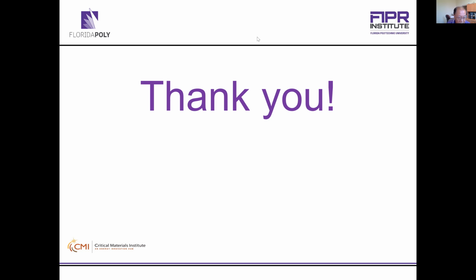Yeah, the first question is from John Carr. The question is, do you have an estimate on the approximate mass of phosphoric acid sludge per ton of phosphate concentrate entering the phosphoric acid plant? Yes, based on industry experience, the amount of sludge generated is roughly 5 to 20%. So that's a large range, 5 to 20% of the P2O5 input. So could be 5% or 20%, depending on how your plant operates. So up to 20%, but at least 5% of the P2O5 input.